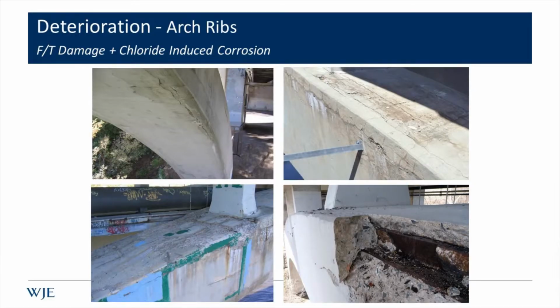The deterioration that was present on the arch ribs in most areas consisted of longitudinal cracking over the outer corners, both at the top outside corners and then also at the lower corners, as you can see in the upper left photo. And unfortunately, as cracking developed, generally as a result of corrosion, that allowed moisture to ingress to the level of the steel. And that moisture, given our climate, can freeze. And you can get freeze-thaw damage, which results in more cracking, which can let more chloride in, and it can become a downward spiral, if you will.